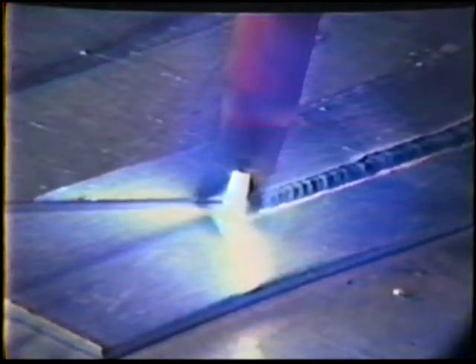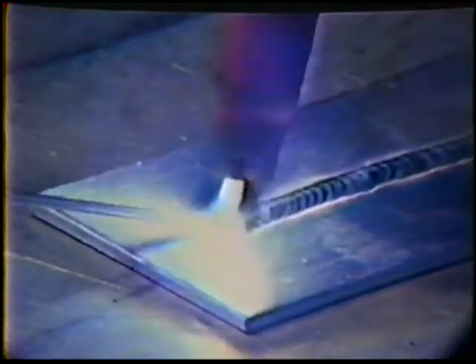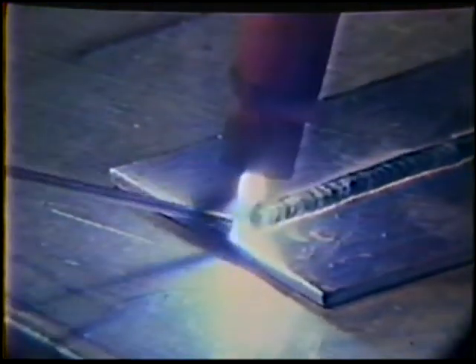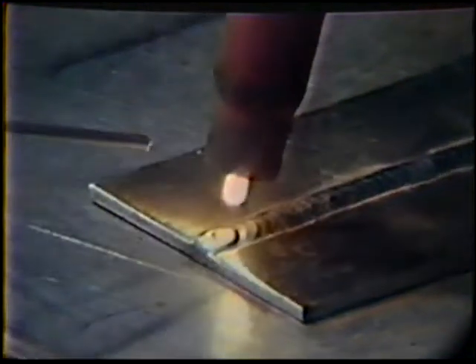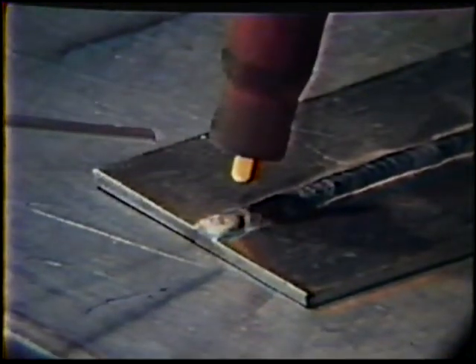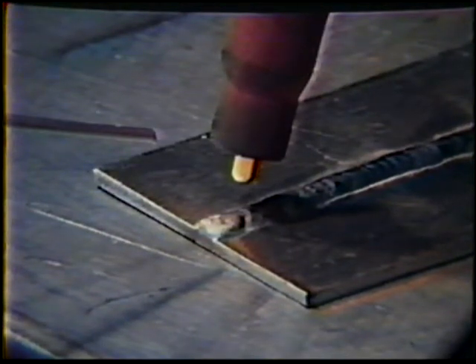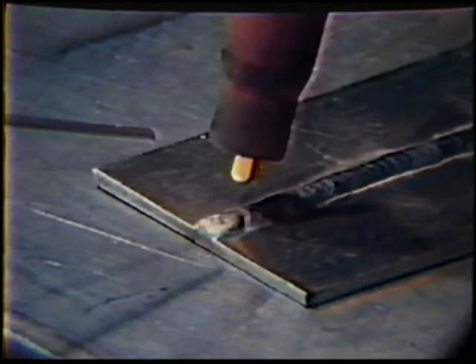As you move along the joint, it may be necessary to reduce the current to compensate for the buildup of heat in the aluminum. This is done by releasing the foot pedal a small amount. At the end of the piece, slowly decrease the current as you apply filler metal to the solidifying puddle. When the crater has been filled, remove the filler rod and continue to decrease the current until the machine shuts off. Hold the torch in position to allow the post-purge to cool the torch and prevent the puddle from oxidizing.